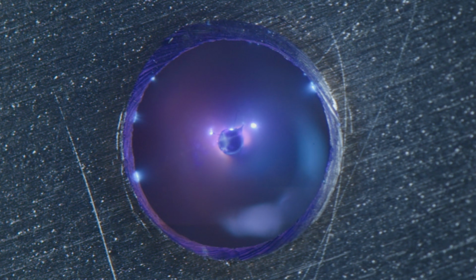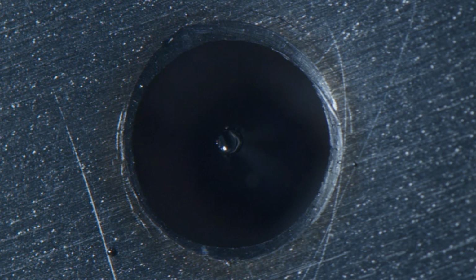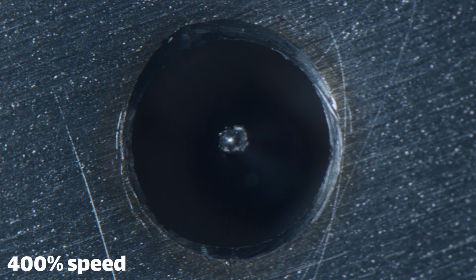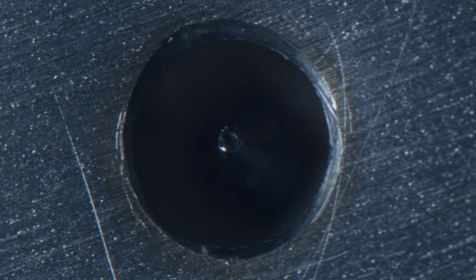We can also see an issue here that I've been suspecting for a while, the oxide skin. In a different clip, there's a very obvious skin of oxide that's resisting the formation of a Taylor cone. Remember, I said the oxide has a really high surface tension, and so it's going to take more voltage to form a Taylor cone than fresh gallium. Eventually, it explodes outwards and is replaced with fresh, shiny gallium. Because this is in vacuum, that oxide skin doesn't reform, which means the new gallium has a much lower surface tension and is far more likely to form a Taylor cone.